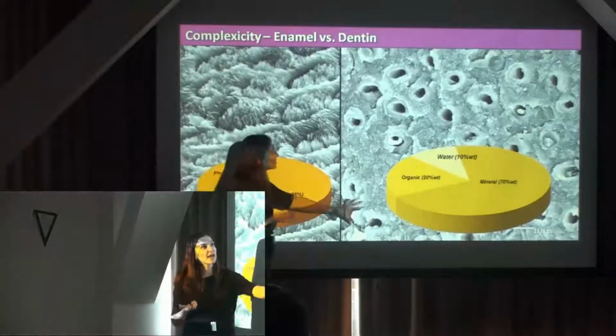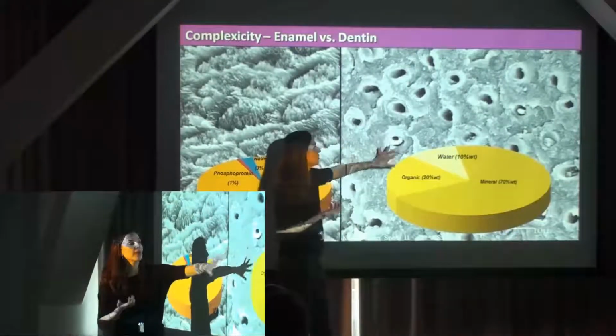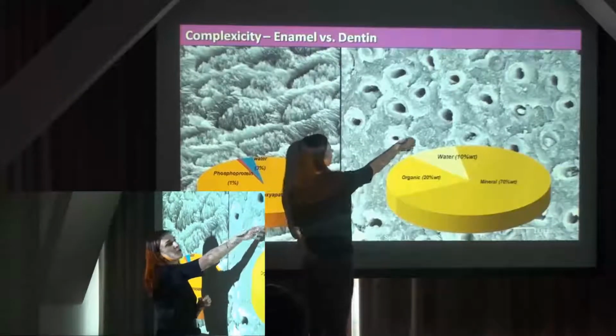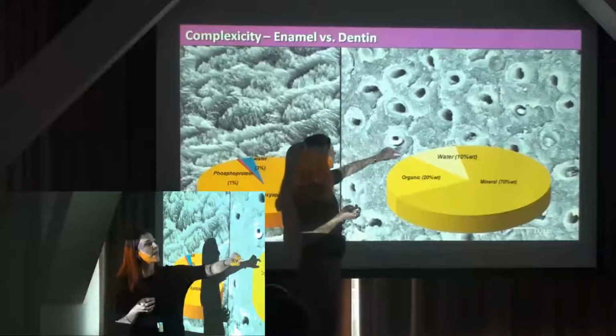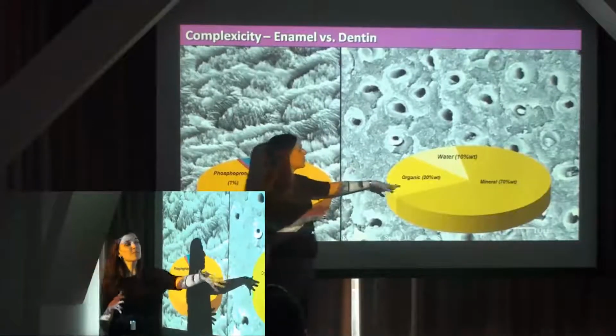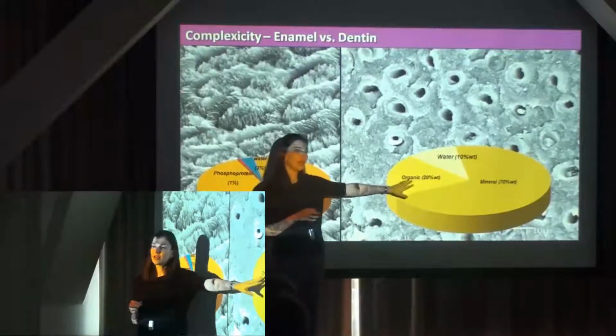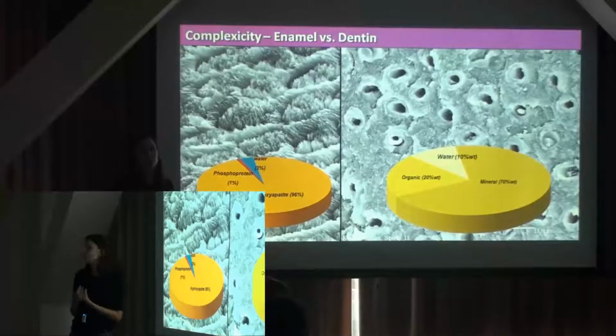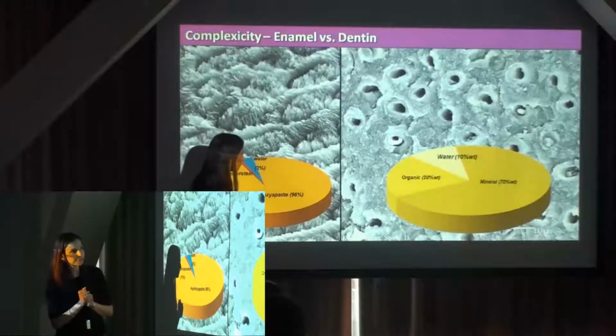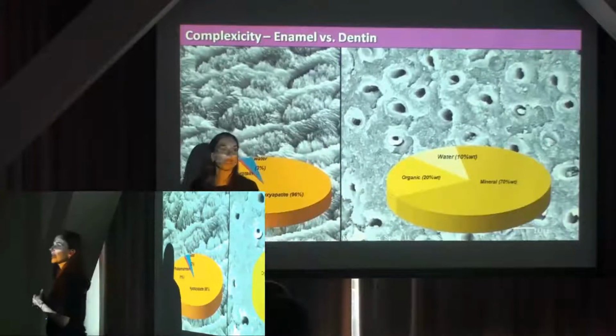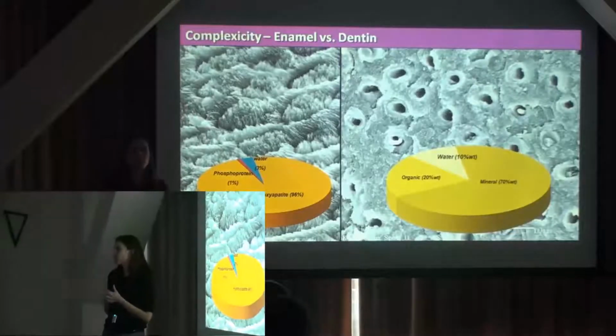So the bulk of the tooth is made out of dentin, which is on the right here, and you've already seen some pictures. You see the intertubular dentin and the highly mineralized intratubular dentin. By weight, it's about 70% hydroxyapatite, 20% organic content, and 10% water. By volume, it's about 50-50 mineral and organic. Of this 20%, 90% is type 1 collagen, and the other big family would be the phosphoproteins, followed by proteoglycans.